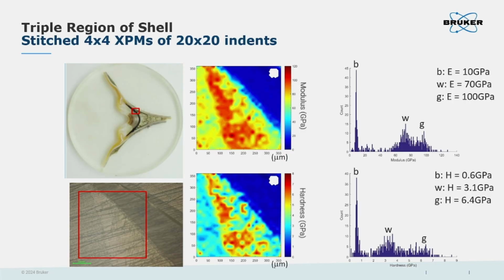Using the technologies Jimmy just mentioned, we design the indentation array, and we pick an interesting region to make the indents, and then we can get a large number of hardness and modulus values. Therefore, we are able to have the hardness map and modulus map together with the histograms. So this is the very first example I would like to show you, related to biomaterials with higher mechanical properties of hardness and modulus. This is for the structure of shell.